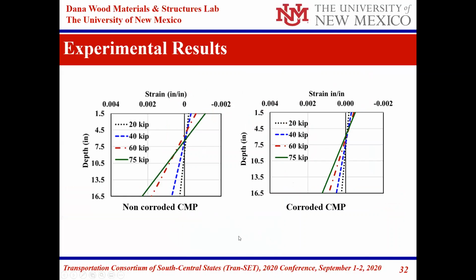We look at the strain. How is the strain? The strain is important for us because it tells us if there is a load transfer or not. And you can see the strain in the case of non-corroded and the strain in the case of corroded. So there is a complete strain compatibility across the system up to the failure load, which is 75 kip, which means basically that the epoxy grout used enabled developing a complete composite action.